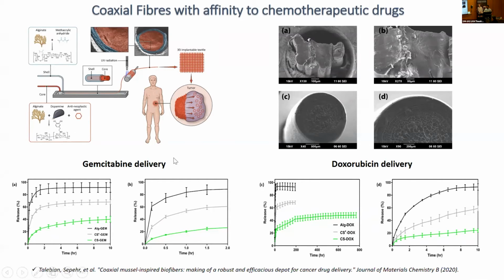Anyway, after we've done these studies, for gemcitabine, we got a really short release profile, which is associated with the small molecular weight of the drug, as well as some functional groups on the molecule.